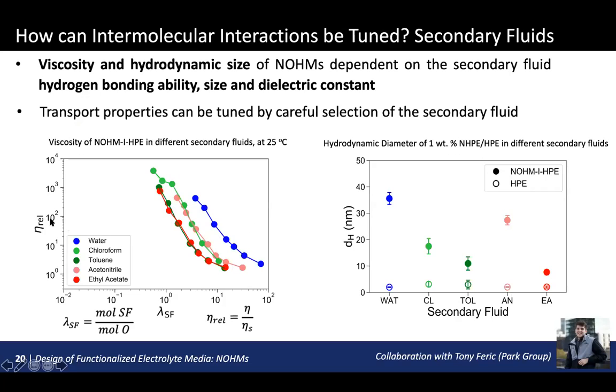So this is, again, viscosity of NOHMs mixtures. If we look at the plot with water, we see quite high viscosities because water is able to hydrogen bond with the groups in our polymer chains. However, if we look at another secondary fluid that has a lower polarity, such as toluene, we can actually reduce the viscosity of those mixtures significantly. And again, DLS was useful to understand this process and relate it to the changes in the canopy. So we see the size of those polymer chains is changing based on the chemistry of the secondary fluid.